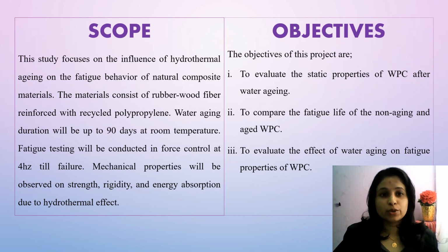Moving on to the scope, this study focuses on the influence of hydrothermal aging on the fatigue behavior of natural composite materials. The materials consist of rubber wood fiber reinforced with recycled polypropylene. Water aging duration will be up to 90 days at room temperature. Fatigue testing will be conducted in force control at 4 Hz till failure. Mechanical properties will be observed on strength, rigidity, and energy absorption due to hydrothermal effect.